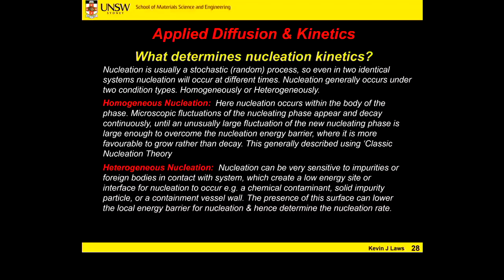Heterogeneous nucleation. Nucleation is very sensitive to impurities or foreign bodies in contact with our system, because what those bodies will often do is create a low energy site or interface for nucleation to occur. Examples are a chemical contaminant in our liquid or our solid, a solid impurity particle, or even just the containment vessel wall. What are we containing our reaction in? The presence of this surface can lower the local energy barrier for nucleation and hence determine the nucleation rate.